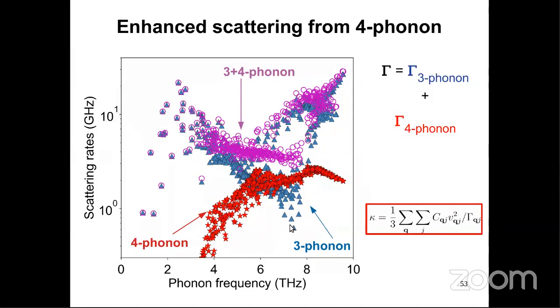So for example, if you see in this region, the blue triangles have been lifted up by a factor of I think 4 or 5 or 6 to these purple points. So there's a dramatic increase in the total scattering rates by addition of 4-phonon scattering. So the denominator is going up in this thermal conductivity expression, so the thermal conductivity is dropping down. And this is the microscopic origin for why 4-phonon scattering is having a dramatic effect on thermal conductivity.